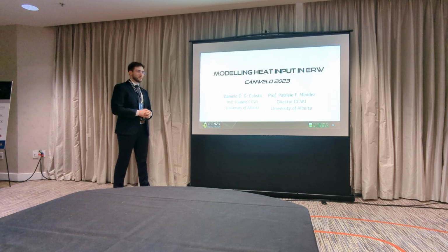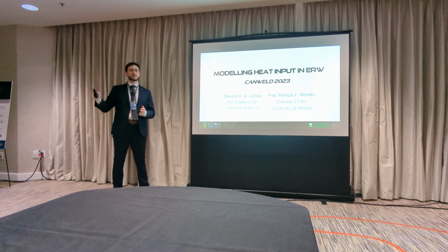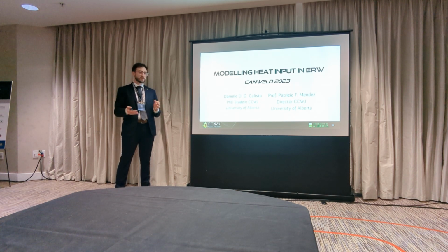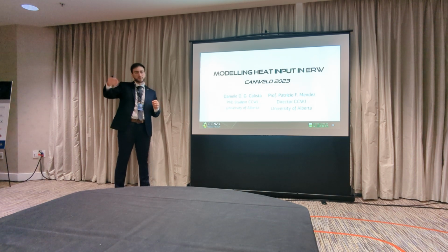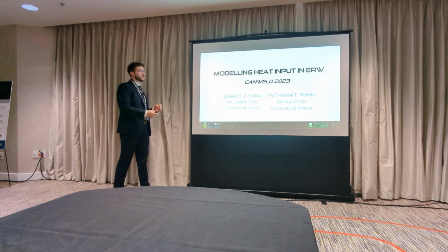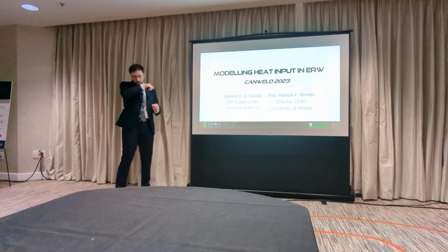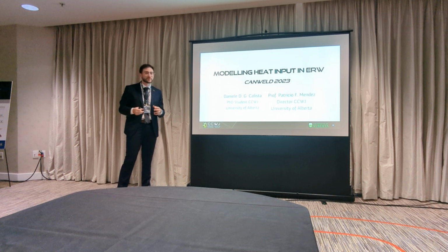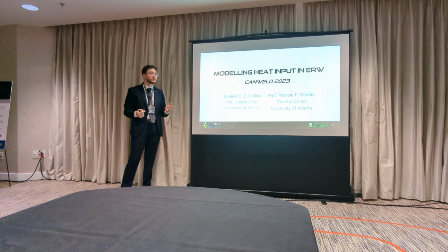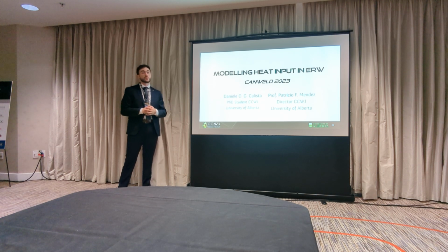So there's really no pre-weld heat treatment because there's continuous heating along the V, so there's really nothing done pre-weld. Post-weld heat treatments include a set of normalizing, annealing and quenching steps that the process uses. But the key thing to note is that these oxides, because they're retained in the weld zone, you can't get rid of them with heat treatment. Once they're in there, there's really nothing you can do. So it has to be addressed at the weld stage.